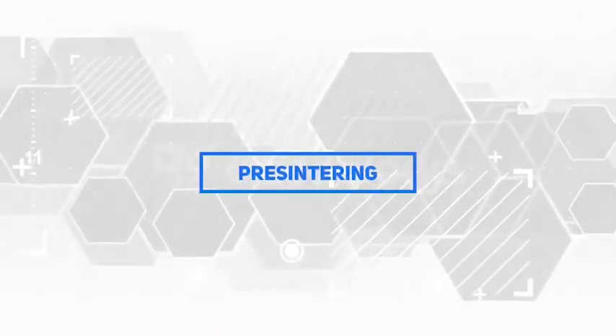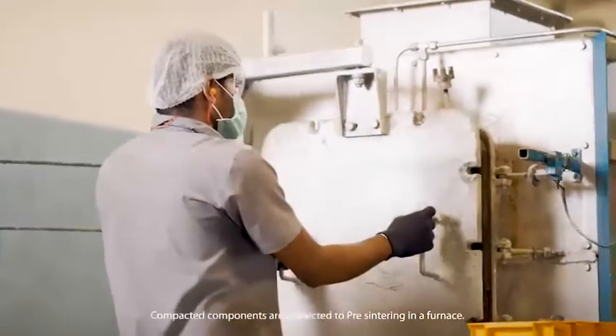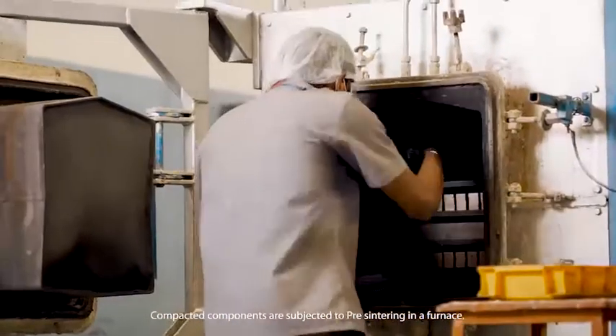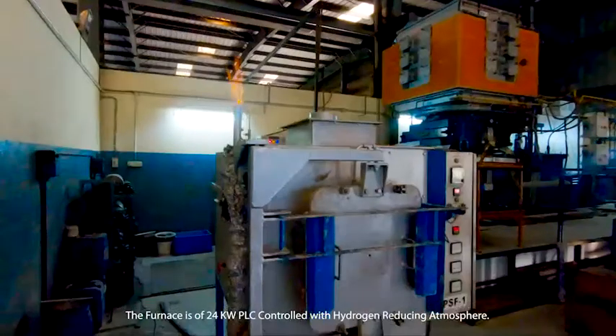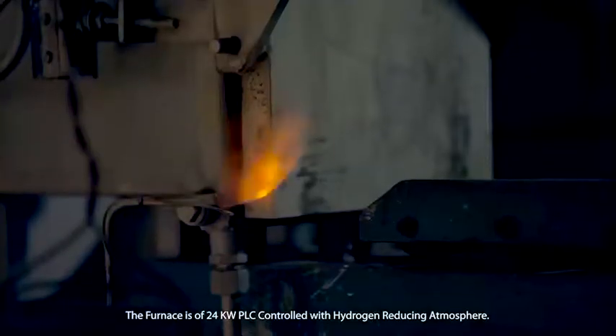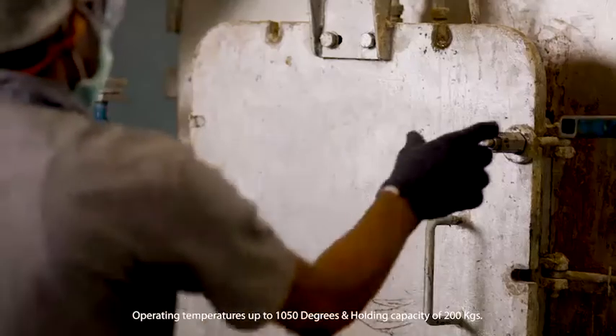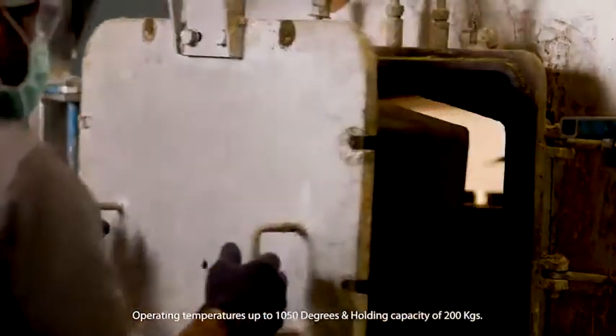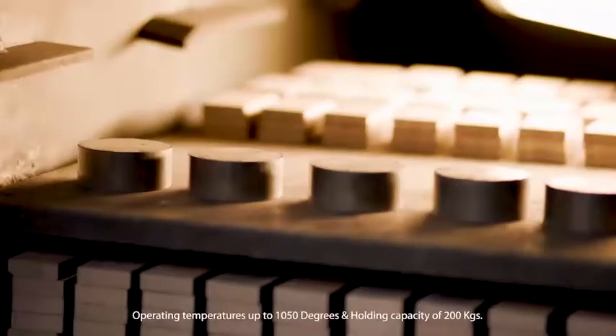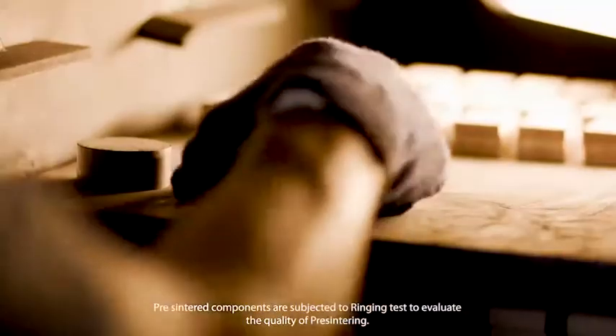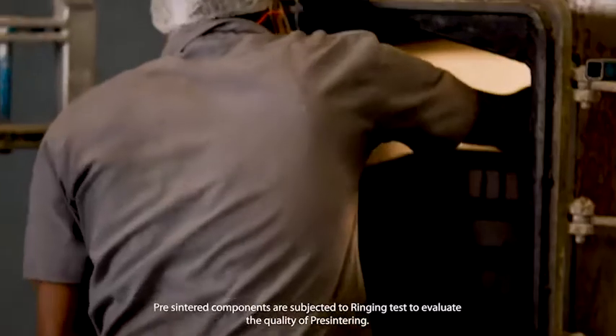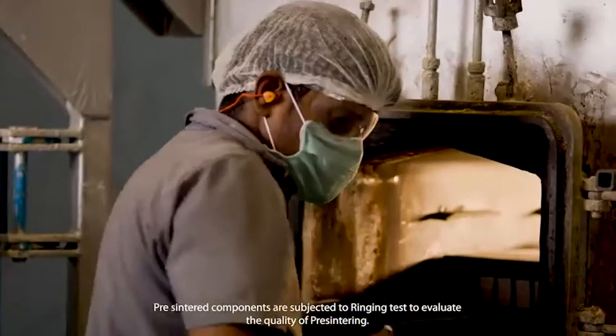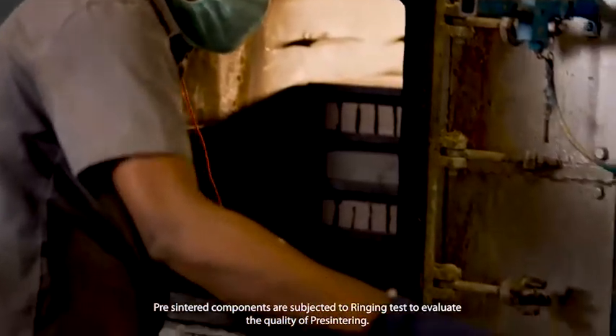Pre-sintering. Compacted components are subjected to pre-sintering in a furnace. The furnace is of 24 kilowatt, PLC controlled, with hydrogen reducing atmosphere. Operating temperatures up to 1050 degrees and holding capacity of 200 kilograms. Pre-sintered components are subjected to ringing test to evaluate the quality of pre-sintering.